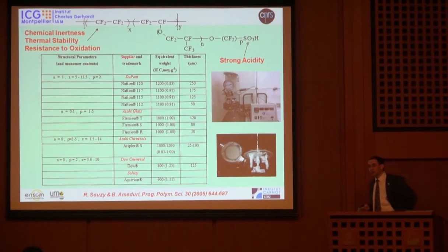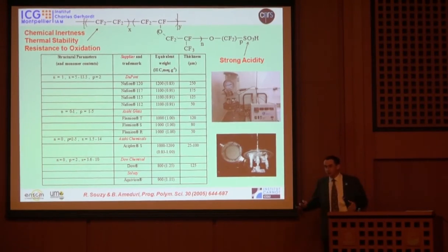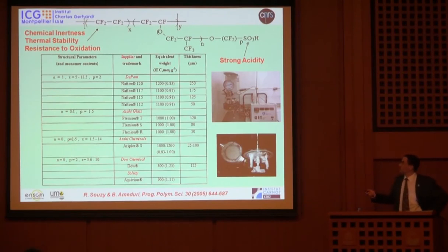This does not homopolymerize under radical conditions, but copolymerizes with TFE. And of course, a lot of work has been done on the kinetics of copolymerization. We did some work with VDF and vinylidene fluoride kinetics in order to copolymerize with this vinyl ether. This is a specific vinyl ether which can be produced by different companies, just like DuPont, Asahi Glass, Asahi Chemicals, or Dow Chemicals, and more recently by Solvay. So this means that you have different n.